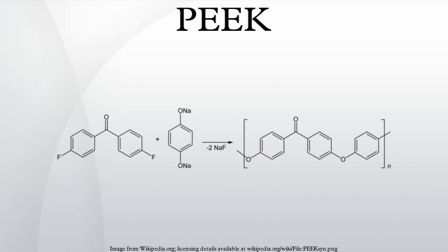Typical is the reaction of 4,4-difluorobenzophenone with the disodium salt of hydroquinone, which is generated in situ by deprotonation with sodium carbonate. The reaction is conducted around 300 degrees Celsius in polar aprotic solvents, such as diphenyl sulfone.